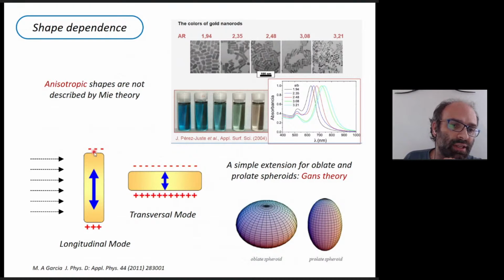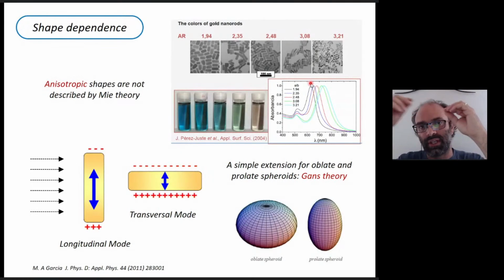And here the very important thing is that you have two modes that can be excited by light. One is the longitudinal mode, so along the long axis of the nanorod. And the other is the transversal mode, so along the short direction. This means that an ensemble of gold nanorods will have two plasmon resonances if they are free to move in solution. And you can see these spectra, they show you that you have one plasmon resonance here and another one here. And what happens is that the second plasmon resonance, the one shifted to the red, can be tuned over a wide range of wavelengths by changing the aspect ratio of the rod. So if you have a rod with always the same diameter and you increase the length, then you will shift the second resonance, the longitudinal mode, towards the infrared. Very powerful tool to control plasmon resonance position.